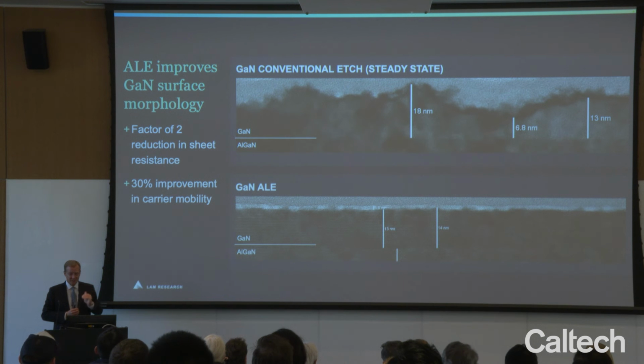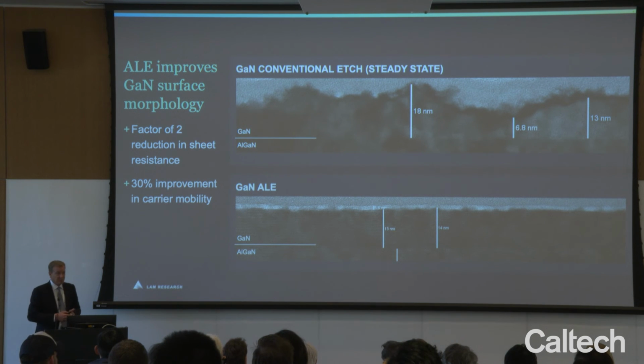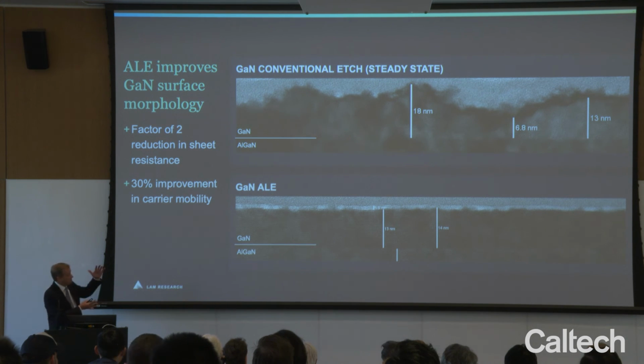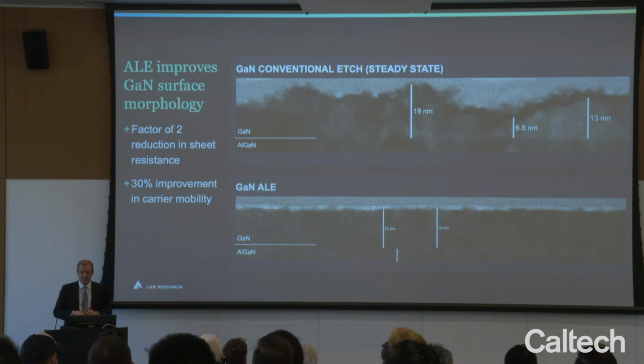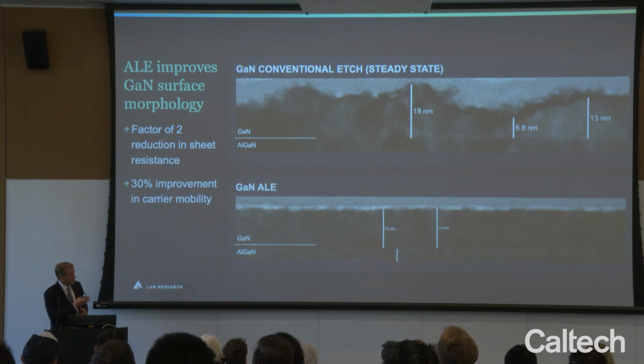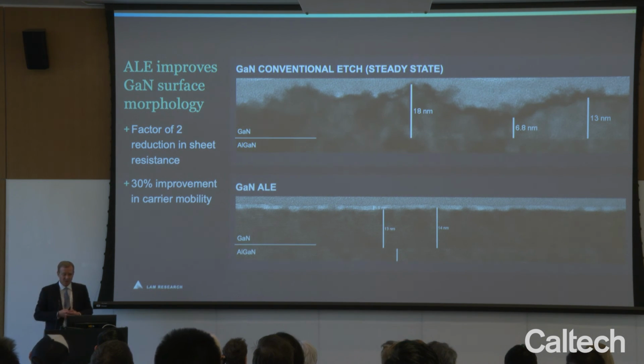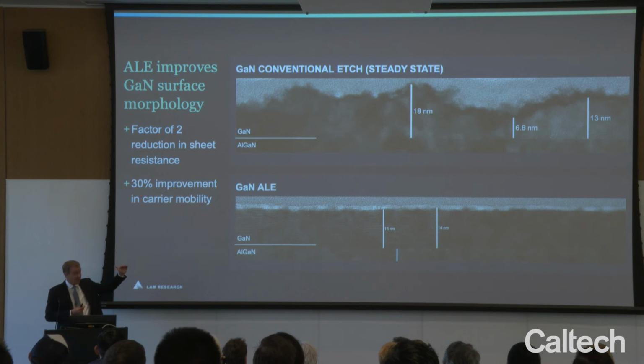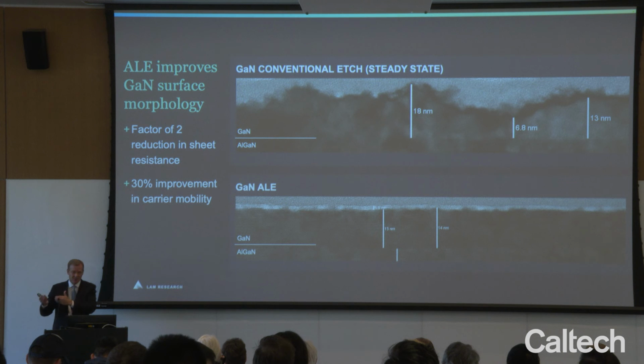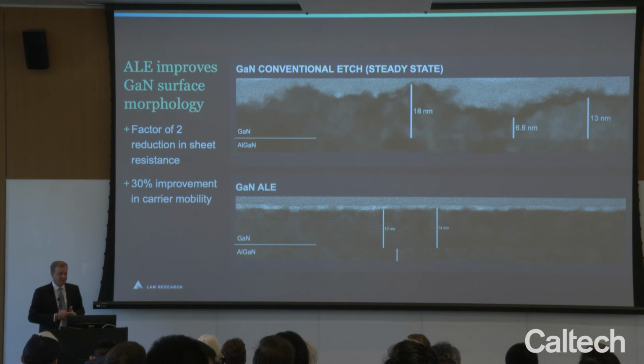you can very precisely control that damage. And you can see that in the images here the differences of conventional steady-state plasma etching versus etching a similar material with atomic layer etching. And obviously the visual difference in the morphology is very obvious, but what's really important is that we're able to see between the two a 2x improvement in sheet resistance and about a 30% improvement in mobility when we actually change this process. And so we think that this type of work, while it's applied here for gallium nitride, there are many, many other uses for atomic layer etching as we continue to shrink not only the size of features, but also look to use different types of materials which are more prone to damage during conventional processing.